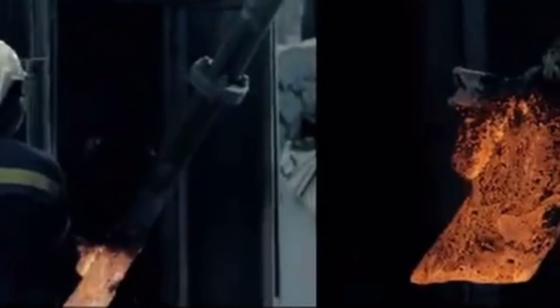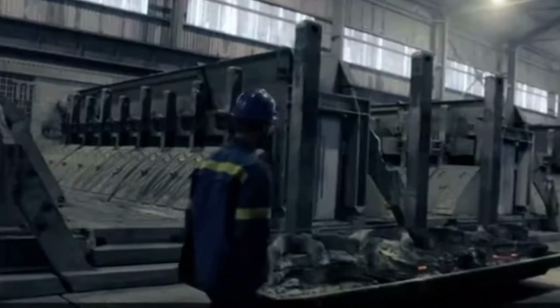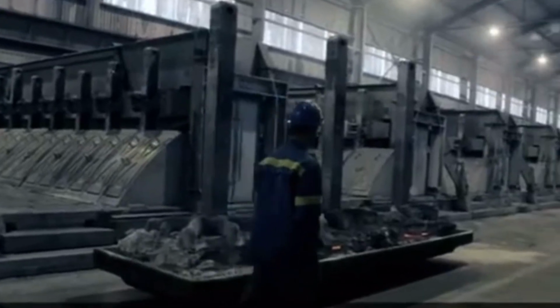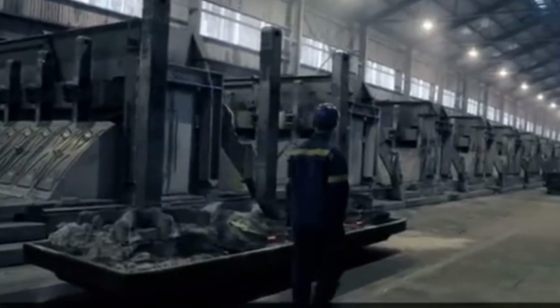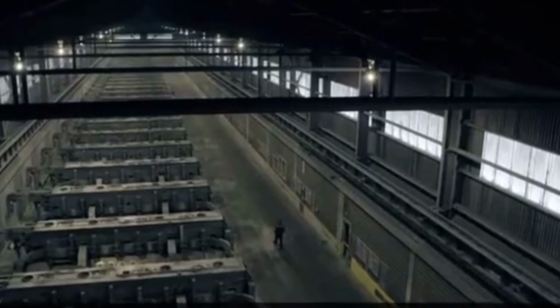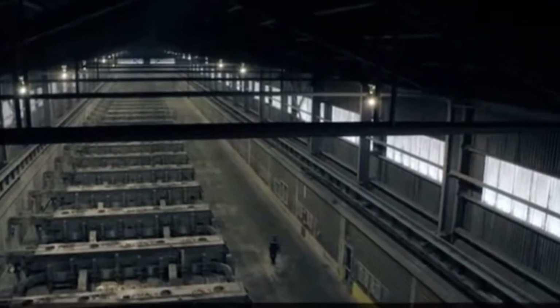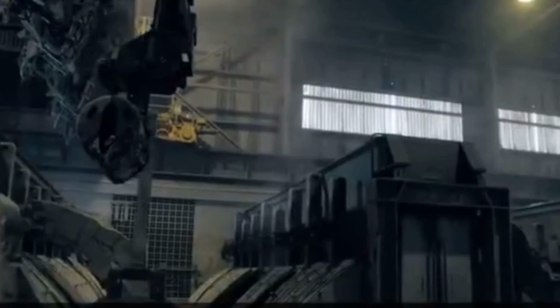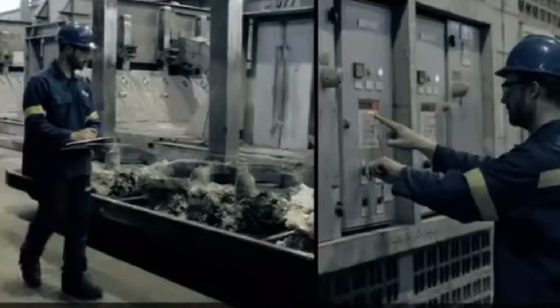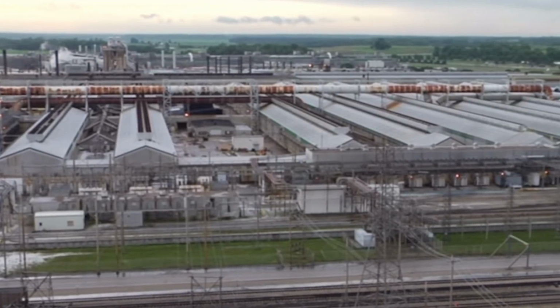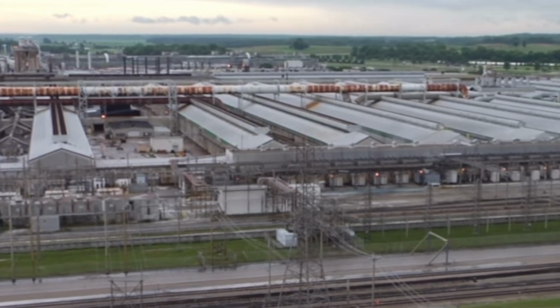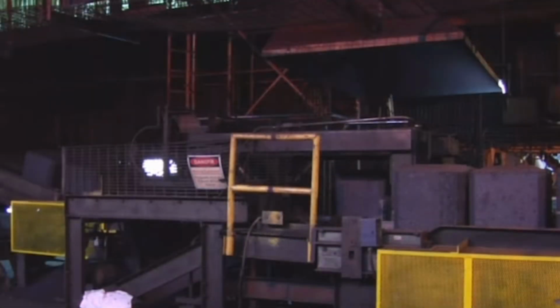As alumina dissolves, it undergoes electrolytic decomposition, yielding a layer of pure molten aluminum at the bottom of the smelting cell. Meanwhile, released oxygen molecules gravitate towards the carbon rods, eventually escaping in the form of carbon dioxide. In its molten state, the refined aluminum is carefully extracted from the smelting cells, transferred into crucibles, and then poured into furnaces. Here, additional elements can be introduced to create aluminum alloys tailored to specific end product requirements.